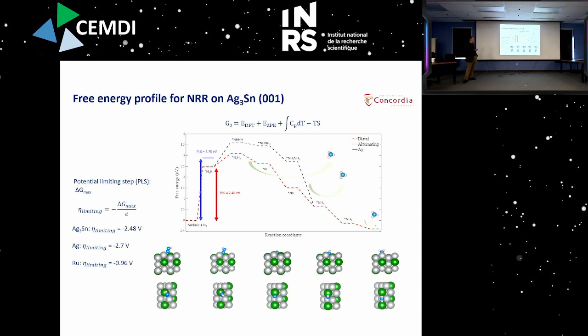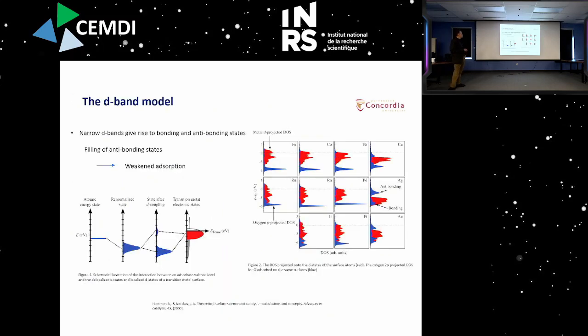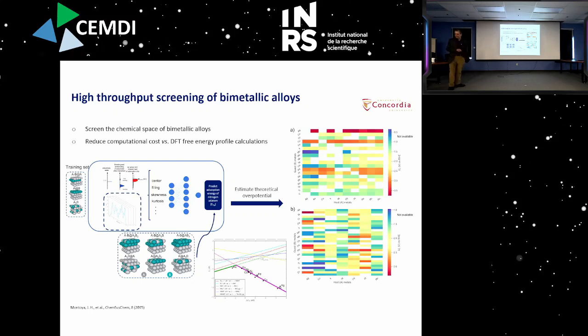It's only a 10% improvement, and this is really nothing comparable to the electrochemical potential used in actual catalysis of the NRR, such as on ruthenium catalyst. A potential of about 1 volt is sufficient to get the reaction to proceed. So really, we're trying to get under 1 volt overpotential in our design of effective catalysts. So I will pass on the D-band model here for the sake of time.